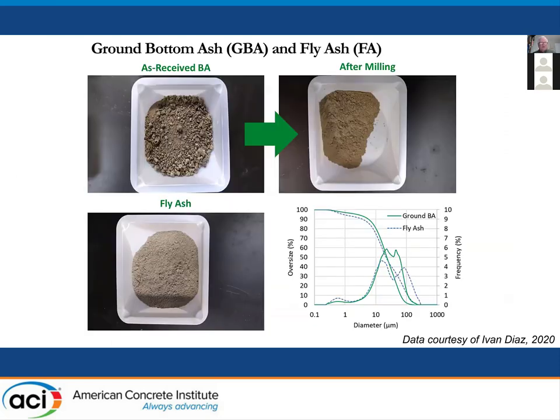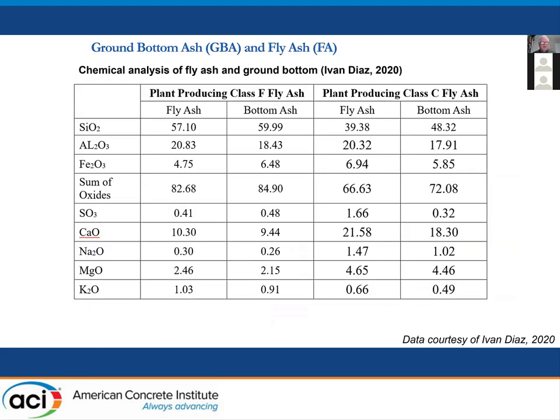If you take the bottom ash and mill it, on the right, it looks a lot like fly ash, and it just shows in the particle size distribution. You can get the same particle size distribution from ground bottom ash as you can with fly ash from the same source. And again, the chemistries are almost identical.